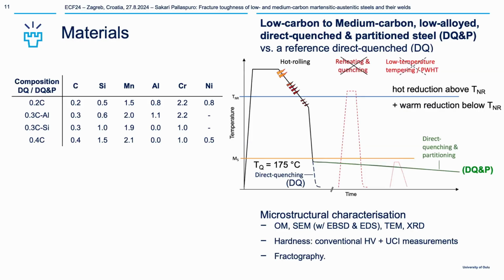So let's proceed quickly. Three different groups of steel: 0.2 carbon, 0.3 carbon, and 0.4 carbon. We did this in our laboratory hot rolling mill. In short, we did hot rolling and quenching directly after the final rolling pass, and either we did direct quenching to the ambient water temperature, or partitioning with an interrupted quenching temperature, with the idea that we can retain more austenite in the microstructure. How it is done, and what kind of morphology results, will dictate completely the properties.